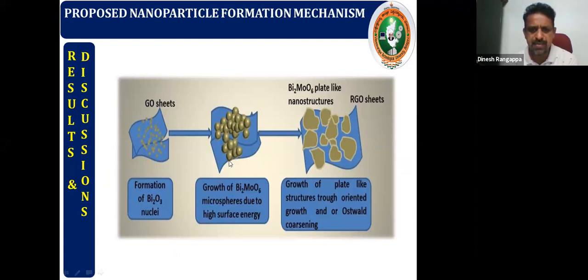So this is just the mechanism of formation. In the beginning, on the graphene oxide sheet, bismuth oxide nuclei formation occurs with increasing supersaturation. Then growth of bismuth molybdate microspheres occurs due to high surface energy. Then with increasing reaction time, these microspheres form a plate-like structure with oriented growth and Ostwald coarsening effect.